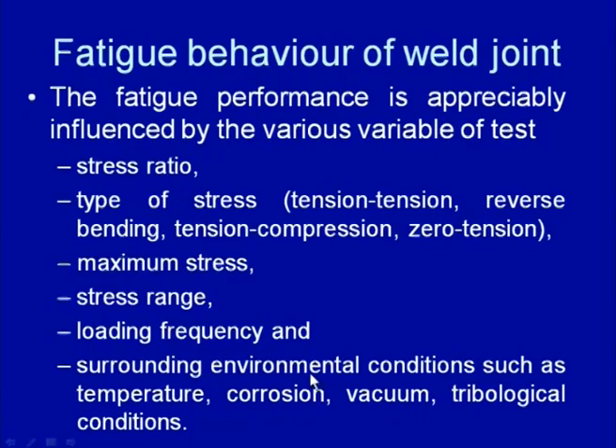And then, if any special kind of environment is applied for conducting the test, like low or high temperature, corrosive atmosphere, vacuum, or some tribological conditions like fatigue testing under fretting conditions, or abrasion, erosion, or cavitation conditions. Depending upon the conditions in which the fatigue test is to be conducted, a suitable environment is developed, and that is reported.